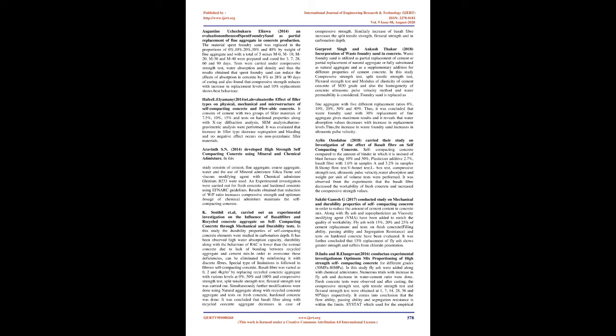Tests were carried out for compressive strength, water absorption, and density, and the results obtained show that spent foundry sand can reduce the effects of absorption in concrete by 8% to 28% at 90 days of curing. It was also found that compressive strength reduces with increase in replacement levels, and 10% replacement shows the best behavior.